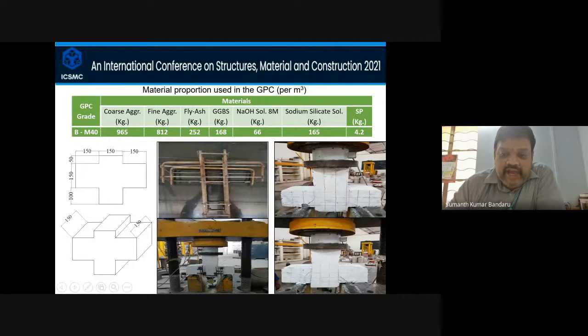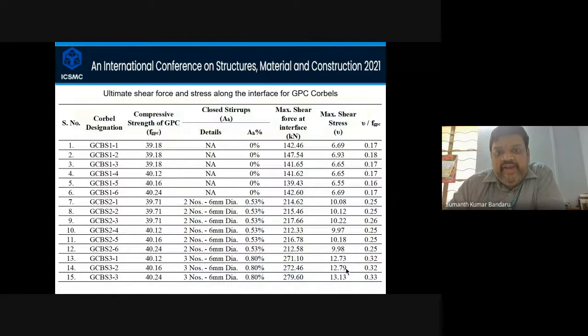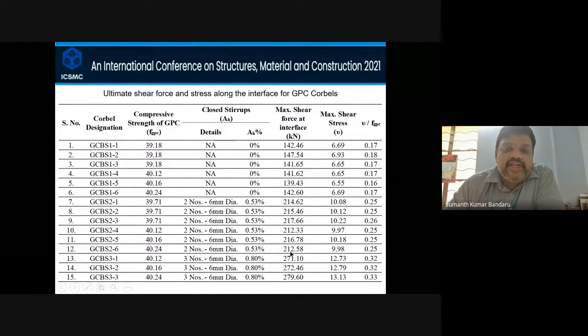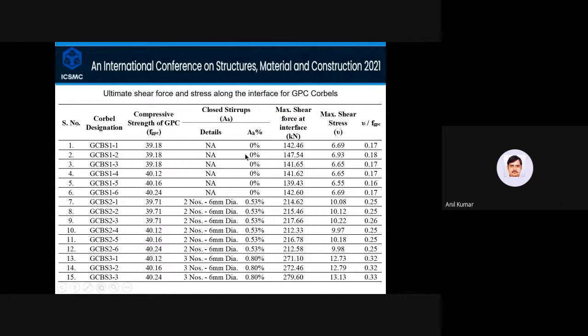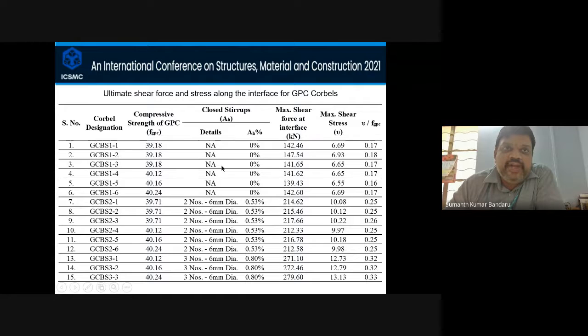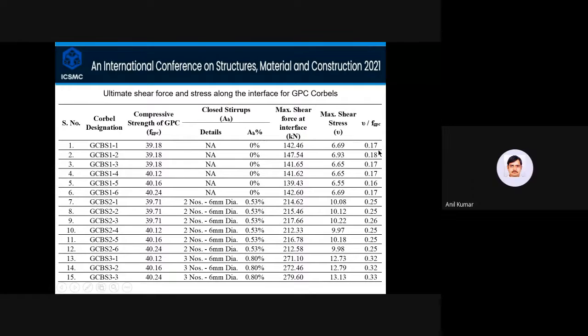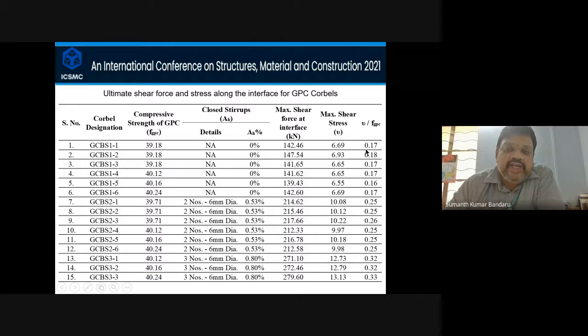This is the non-reinforced, and these are the stirrups. Wherever the stirrups are there, we got a series of diagonal cracks, sir. And this is for M40 grade. These are the maximum shear forces at the interface. Where 0.8% we got around 279, for 0.53% it is around 215, sir. Without the shear reinforcement, meaning the main reinforcement crosses the interface but no stirrups are there at the interface, it is around 140, 145. So it is around 0.17 times your compressive strength, sir.